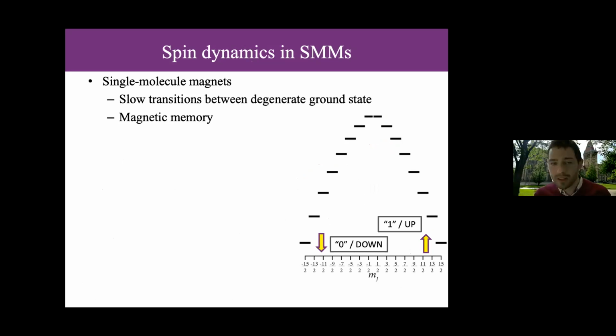So single molecule magnets, again, I'm not going to labor this point too much, but we have a series of electronic energy levels that are separated by the magnetic anisotropy. In this talk, I'll be focusing on lanthanide single molecule magnets, where we have a total angular momentum ground state, which is comprised of both spin and orbital momenta. And so the MJ subscripts, or the projections of the total angular momentum, are the quantum states we're interested in. And these are separated here by the crystal field splitting, which induces the magnetic anisotropy in these molecules. And so we like to think about this energy barrier to magnetic relaxation, where we have this easy axis magnetic anisotropy, where we have a ground state with a very large projection of the magnetic moment that is doubly degenerate, and we can assign an up and a down notation to these lowest energy doublet states. And this is where we like to store our classical information in a single molecule magnet.